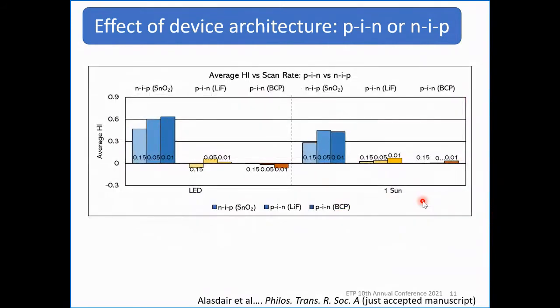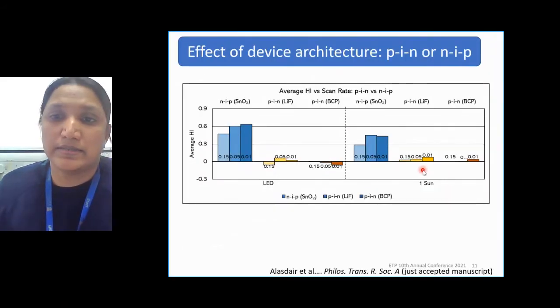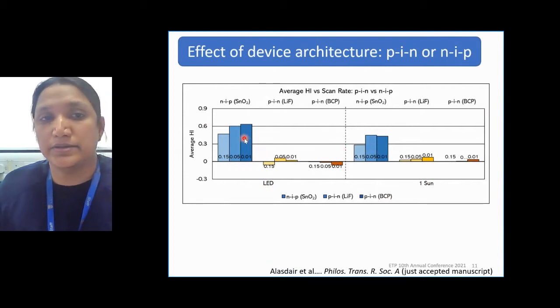This is a summary of average hysteresis indices of more than 30 devices that we have fabricated. Here it summarizes this is for one sun illumination, and this is for white LED illumination under indoor conditions. Here we can see that the PIN devices consistently show less hysteresis effect under both illuminations, whereas the NIP devices show a higher hysteresis effect and it increases under the indoor illumination.